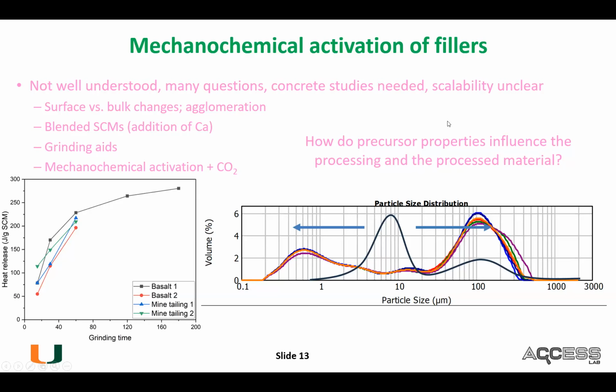You're not going to do any concrete testing unless you have at least 10 pounds, but probably closer to 40 pounds of material. That's probably the minimum amount you need to actually do any concrete testing. So you can have the nicest technology in the world, but if you're only manufacturing a few grams of it, concrete testing is some time away. For this technology, for example, we can't really make concrete because we only make about 200 grams every 15 minutes. So far, we haven't even made concrete, which is similar to what most of the others are doing, or not doing.